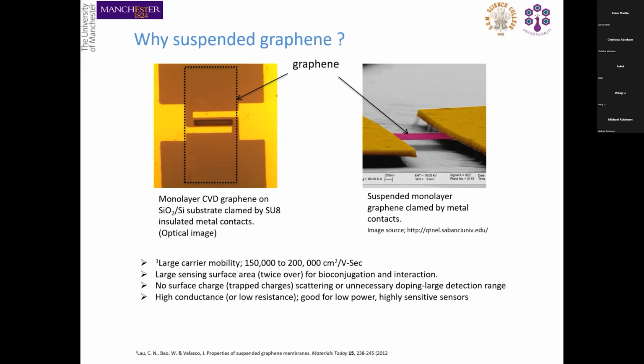And at the same time, other contamination can also dope the graphene from its pristine property. So the original property of graphene is affected as soon as it goes on a normal surface. That's why we need to remove the surface underneath so that we can get the pristine graphene properties. For example, in the picture on the right side, there's a graphene film connected between the two metal electrodes, and there's no surface underneath. So it's freestanding. When it is freestanding, you get all those high quality properties, with mobility of 150,000 to 200,000 centimeters squared per volt second.